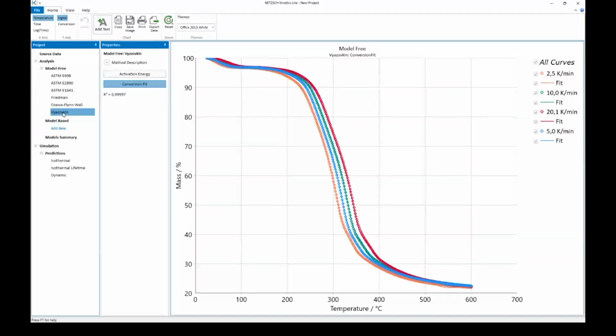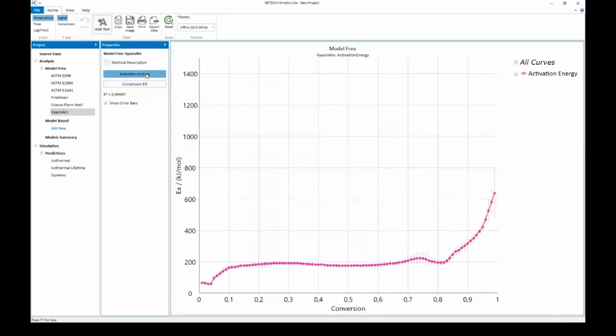And after that, we can compare them and see the best one is Vyazovkin. Here, Vyazovkin, we have very nice solution. We have activation energy as a function of conversion, and we can use this result for predictions and for all other things which are necessary.